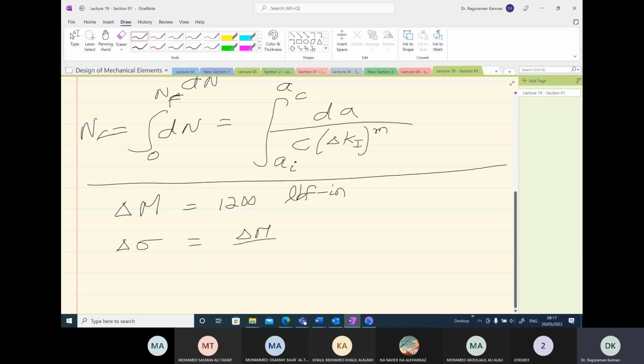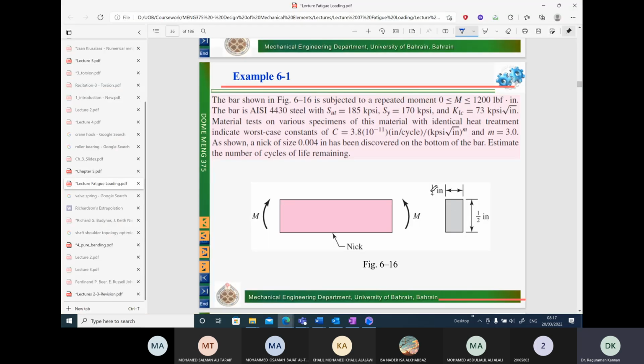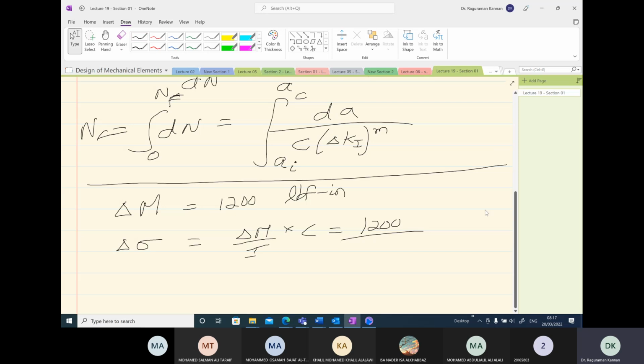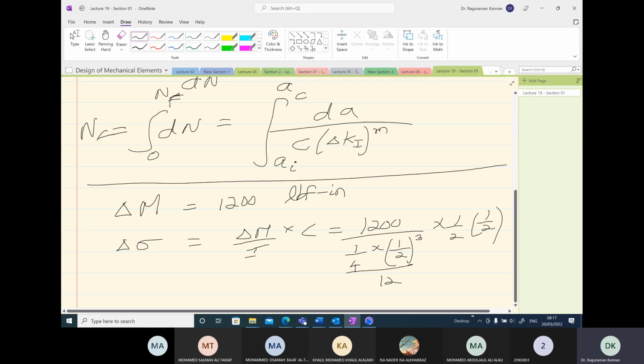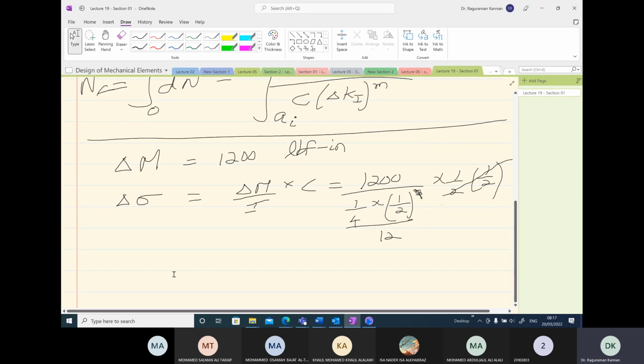Delta sigma will be delta M over I times c. So delta M is 1200. The I for the cross section is 1/4 and 1/2 in the height, so b h cubed over 12, and multiplied by half the length of this, 1/2 of 1/2, and we can basically cancel off these two, and here we can simplify further. Rather, we can calculate the values directly.